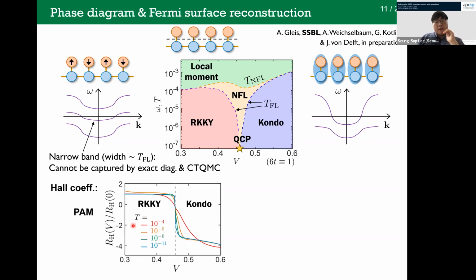First, we have computed the Hall coefficients across this phase transition. When you look at just the lowest temperature, which is very close to zero temperature, the Hall coefficient shows a jump. And also it changes the sign. It means that the charge carriers change their nature, I mean, from hole to particle or particle to hole. As we go to the higher temperature, this jump gets smeared out because we are now crossing this non-Fermi